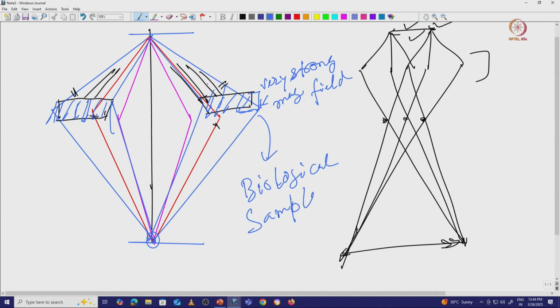So, when we want to image, we already discussed that C1 is the spot size, right. So the spot size, and then C2 is intensity, and then this aperture. If we use this kind of aperture, we can block lots of electron dose, and then we can control the electron dose. So, I will stop here.